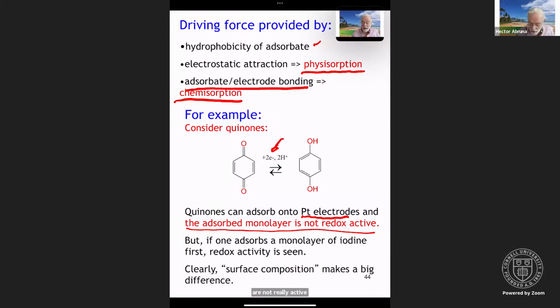And so clearly, the electrode is having an enormous influence on this process. However, if prior to that, you take that platinum electrode and immerse it in, let's say, a 1 millimolar solution of potassium iodide, that generates an adsorbed monolayer of iodine on the surface. And if you then adsorb the quinone, it is fully redox active. So you've gone from something that is not redox active to something that is redox active by controlling the composition of the interface. So please don't tell me that the interface doesn't matter. Surface composition is absolutely critical, and as you can see in this example, it can be the difference between something being active and non-active in an electrochemical context.